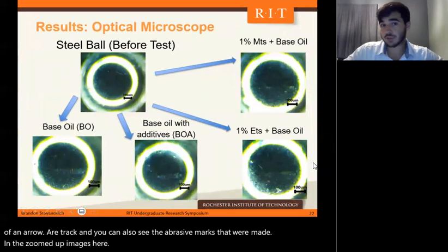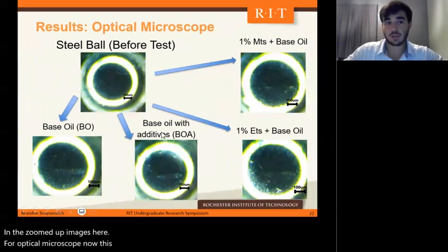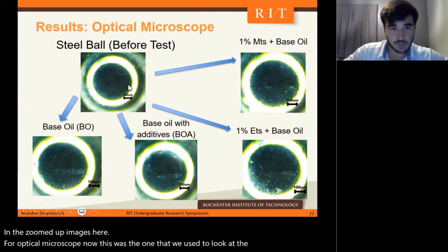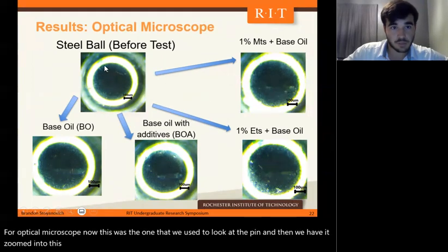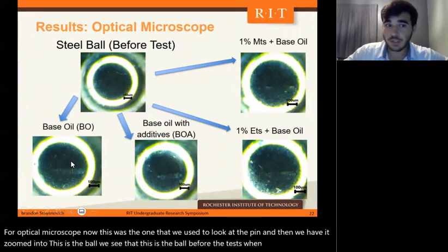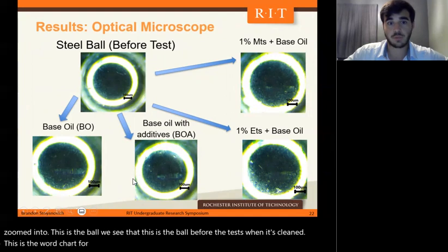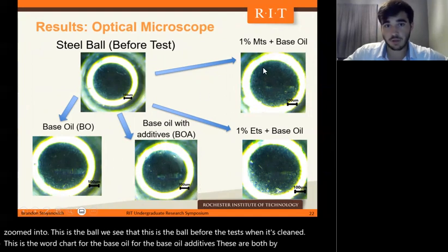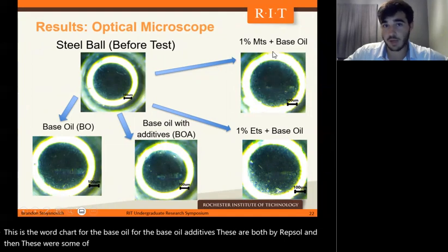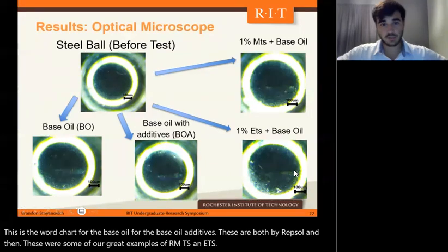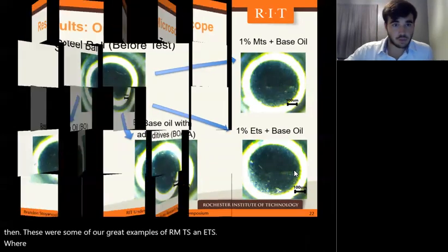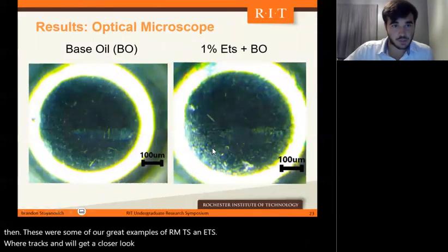For our optical microscope, this was the one that we used to look at the pin, and we have it zoomed in. This is the ball. We see that this is the ball before the test when it's cleaned. This is the wear track for the base oil with additives. These were both by Repsol. And then these were some of our great examples of our MTS and ETS wear tracks. And we'll get a closer look with this picture here.